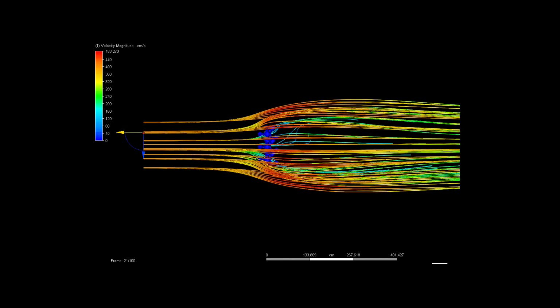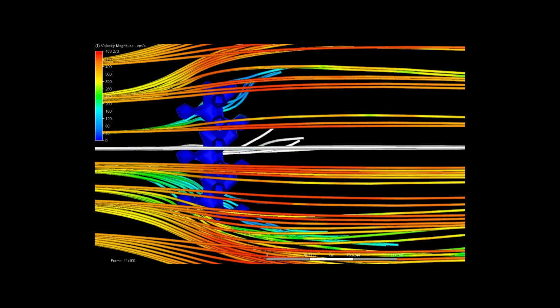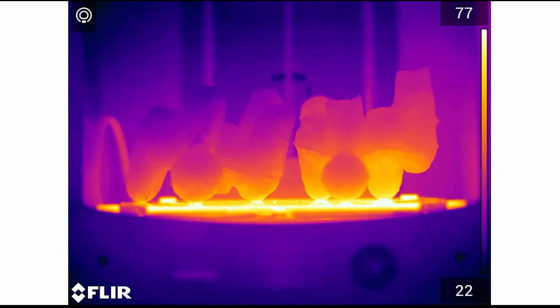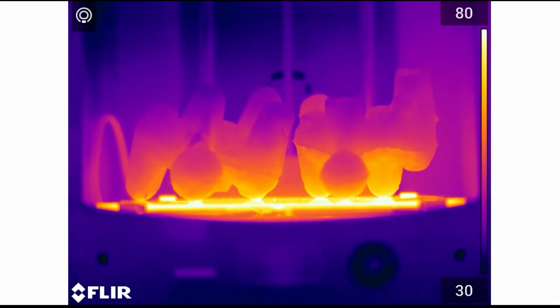CFD analysis further allowed us to speculate on the Venturi effect through air pockets between the bricks, which can potentially allow passive cooling. Developing hollow bricks also allowed internal water flow, creating vertical channels, and can be used as a strategy for water storage and irrigation of the substrate. A thermal study confirmed solid bricks showed more thermal lag than hollow bricks.